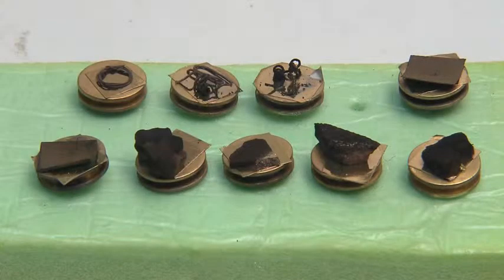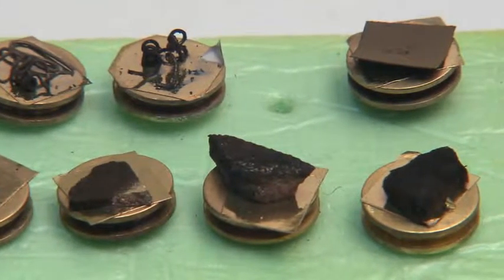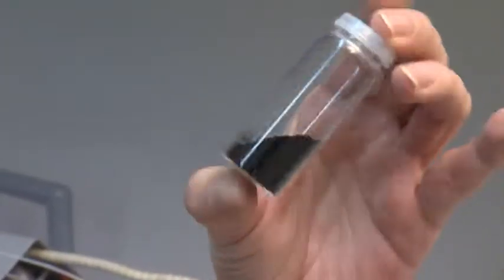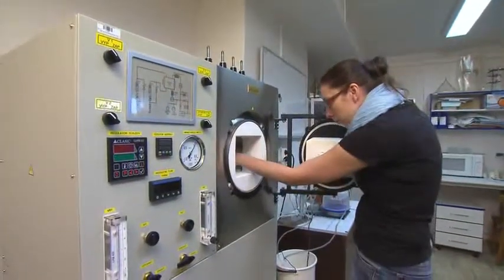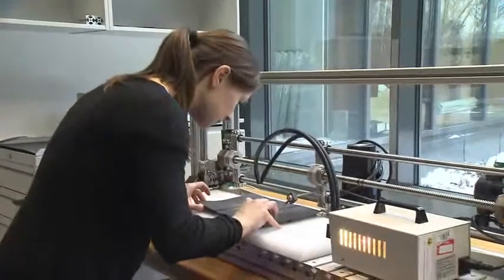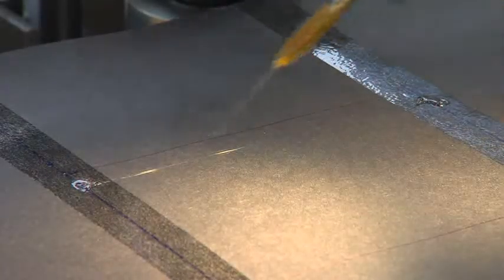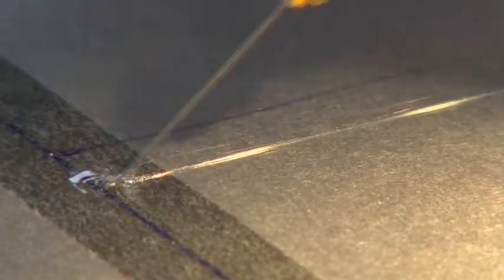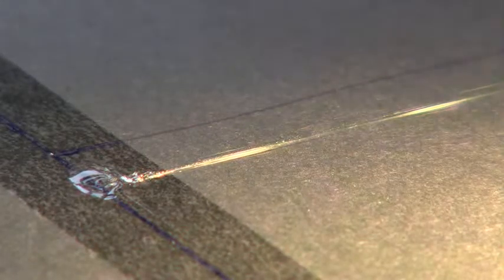We have in our lab also another method to produce not textiles, nanofibrous materials, but nanotubes or nanofibers made of carbon. This method is called chemical vapor deposition, that is based on the deposition of carbon nanotubes due to elevated temperature from, in our case, natural gas. We are working on a quite new technology that is called drawing of individual nanofibers in a mechanical manner using a micromanipulator that we developed, and we are trying to develop such nanofibers as optical probes or electrical probes for, for instance, indication of various chemical agents in the air.